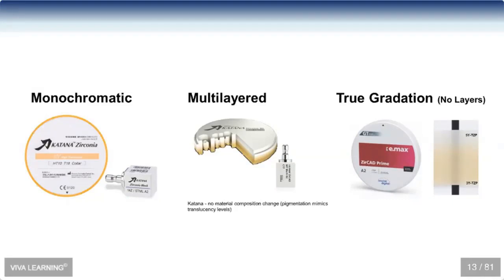And what Ivoclar has done has come up with something that truly deserves the term next generation by coming up with a true gradation. There's literally no layers here. And so as you can see over here to the side, the amazing thing is that it goes from a 3Y, a full strength powder, oxide ceramic, up to a 5Y, a translucent one, at the top with no layers in between, just dispersed, and it's a true gradation from the 3Y up to the 5Y, so you don't have to position your crown at a specific location here so you don't get too much incisal or too much cervical. It's amazing how they've done this, and by blending these 2 oxide powders, these zirconia oxide powders, you've got the high strength 3Y that you have with like a Bruxer material at the margins, and then up at the incisal or the occlusal portion of the crown, you've got more translucent material. So it's truly a mix of different translucencies within one material.